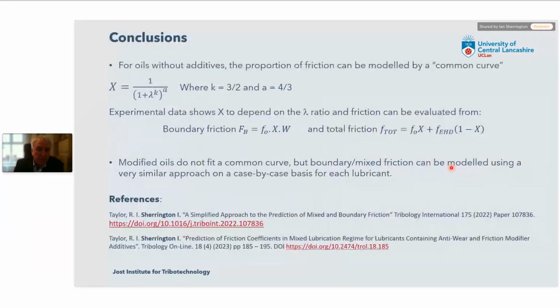So moving towards a conclusion, for oils without additives, we believe we've got a really quite accurate model for predicting friction in the boundary and mixed regimes. It's quick to implement, it's easy to use, and it appears to be accurate because it's based on experimental data. We can also model modified oils, additivated oils. They don't collapse onto a common curve, but you can still use the same technique provided you've got data on a case-by-case basis for each lubricant.